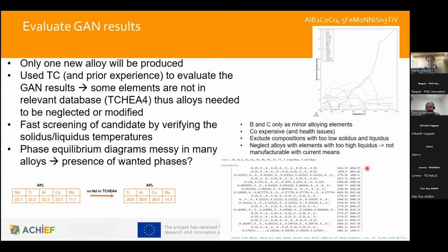So we decided that the solidus temperature for these materials should be more than 1600 kelvins. This is since the application temperature, or the use case temperature, might be up to 1150, so there should be some tolerance to the actual solidification temperature, so that the materials still have some strength left. And also we had to neglect even some more elements, since the database that we used for the evaluation of these materials didn't include every single element that was left first in the selection.